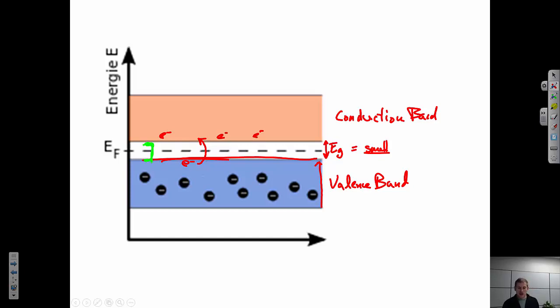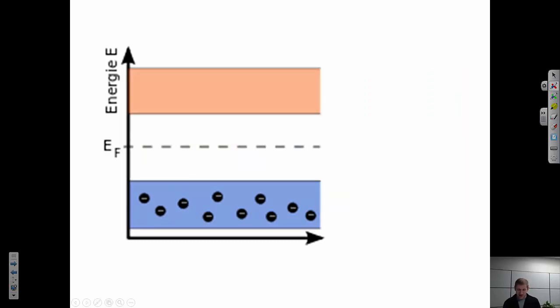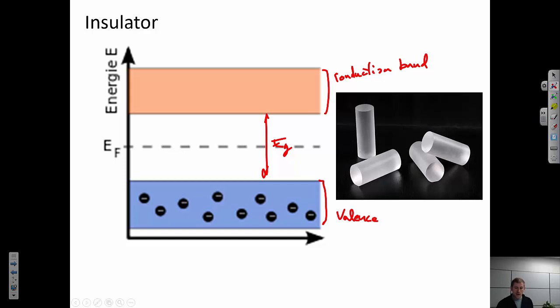In order to conduct, an electron has to have enough energy to get all the way excited up to the conduction band. In semiconductors, this is difficult but not impossible to do, so I have a very small number of available carriers. That's why semiconductors can conduct electricity relatively well under certain circumstances. If we take this picture and start increasing the magnitude of the band gap, it becomes more and more difficult for these electrons to be excited up to the conduction band — this is what an insulator is. An insulator is a material where we've filled up the valence band and there are available energy levels in the conduction band, but there's a very large band gap, making it very difficult to excite these electrons across it.